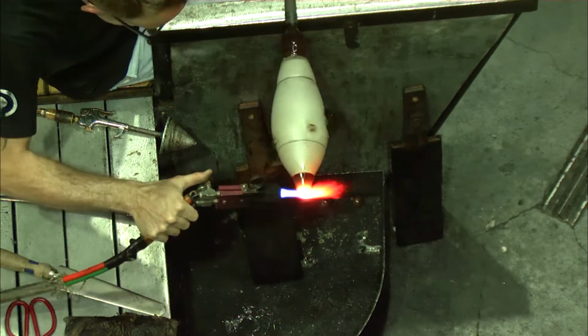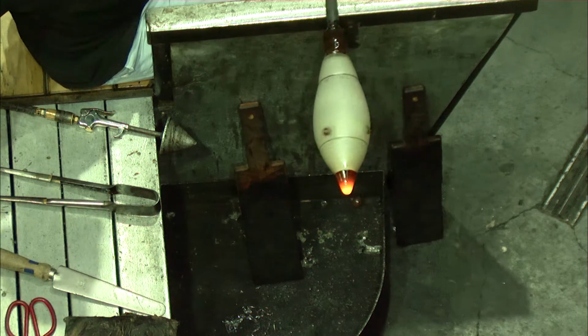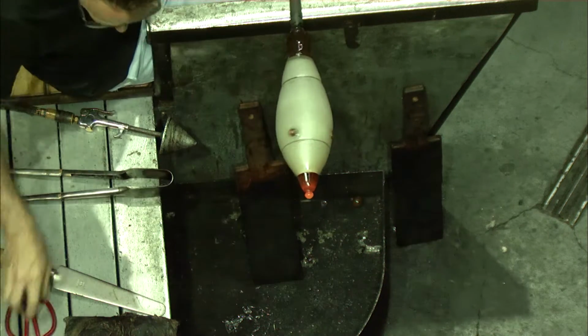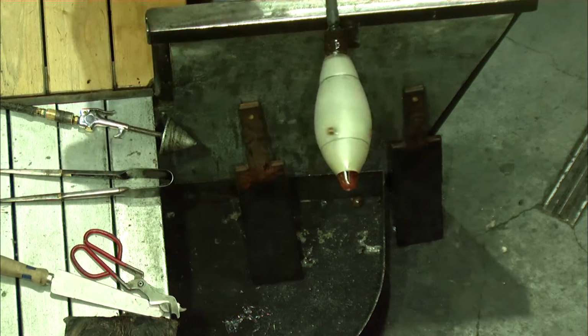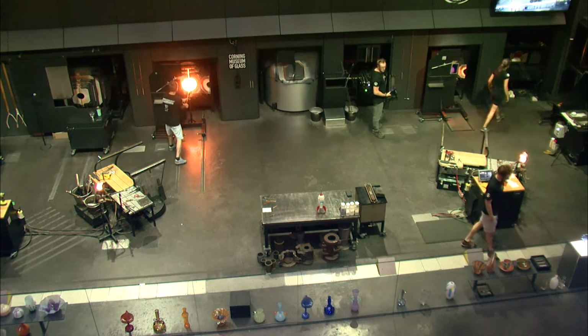The soda ash that we mix in to lower the melting point of our glass can melt away over time, or it can burn out, essentially. We would say it burns out. And then you start getting these inconsistencies in the glass chemistry. And sometimes that ends up being visible. You get these striations in glass. So we typically would only recycle our glass one time.